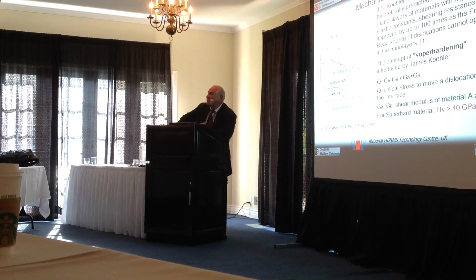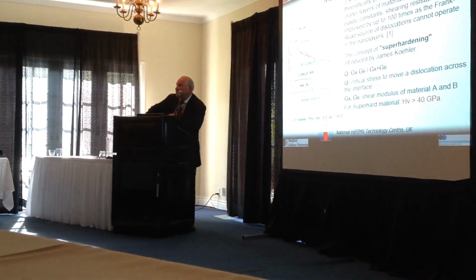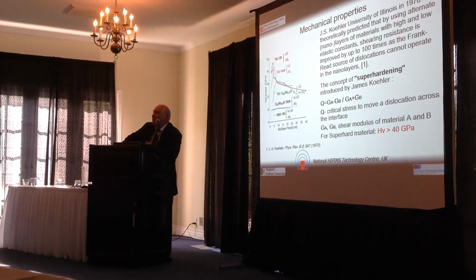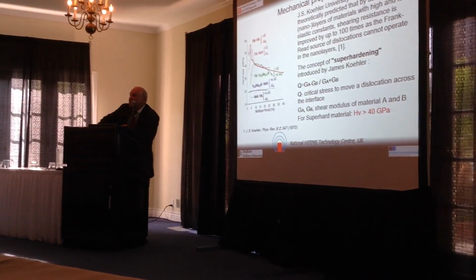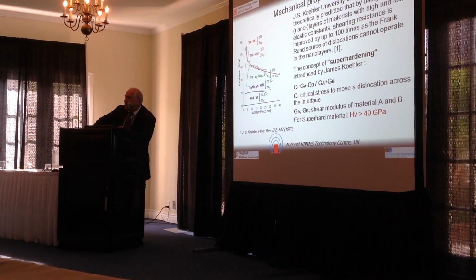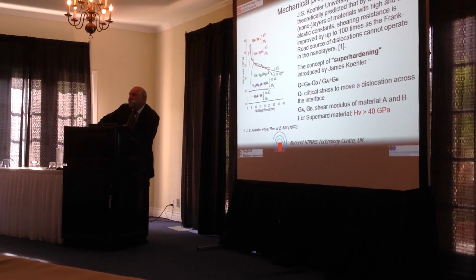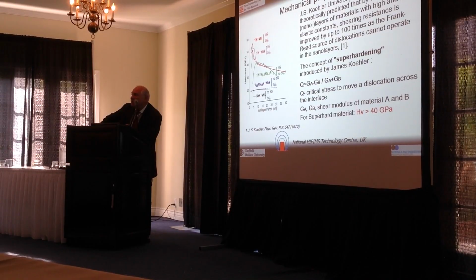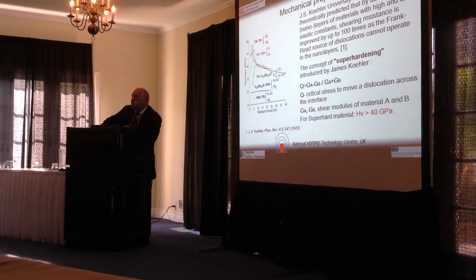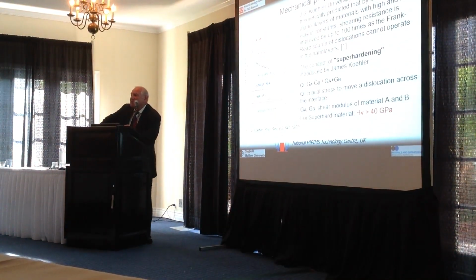And the theory was that if you marry two materials with different elastic constants, then you automatically create a barrier for the dislocation motion, and the energy they need to cross this barrier is proportional to the difference between the elastic moduli. So it was a very interesting concept because this gave in our hands the tool to manufacture man-made new materials.